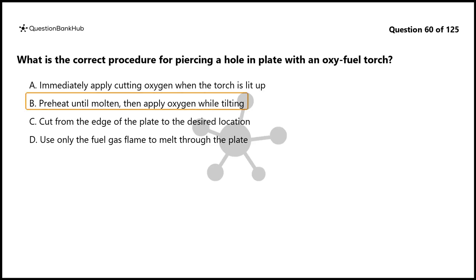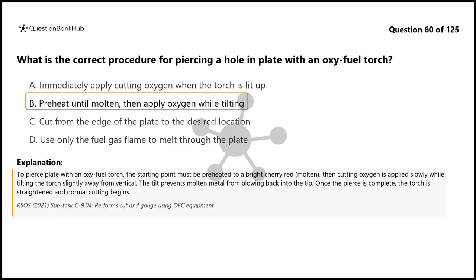The correct answer is B. Preheat until molten, then apply oxygen while tilting. To pierce plate with an oxy-fuel torch, the starting point must be preheated to a bright cherry red, molten, then cutting oxygen is applied slowly while tilting the torch slightly away from vertical. The tilt prevents molten metal from blowing back into the tip. Once the pierce is complete, the torch is straightened and normal cutting begins.